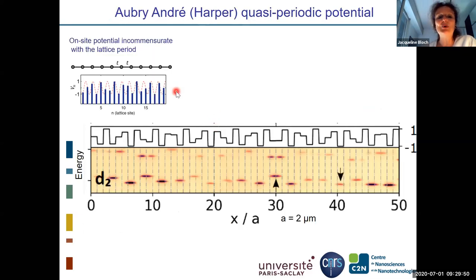Here I want to show you an example of a wire in the Aubry-André case for a large value of lambda. This is the localized phase of the Aubry-André. Here you see what we measure as a function of position along the wire and energy, and I also show the potential implemented on the wire so you can understand how it works. We have very precise control of these wires. In the potential, there are regions with a minimum on a single site, and indeed in the polariton states, we have a mode localized at low energy on a single site.